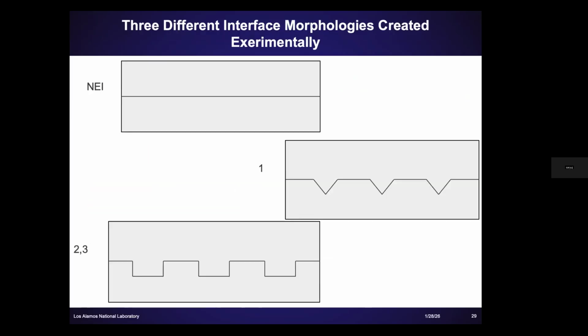How does this compare with experiment or reality? Because molecular dynamic simulations can have their own issues. So to check that, we actually did some experiments. We made three interfaces. One, we basically took two pieces of materials and joined them together using diffusion bonding. Then in one case, we made defects in the titanium. Imagine taking a sharp tool and making a scratch and then doing diffusion bonding. So the interface kind of looked like this versus a square kind of interface. Again, we made the defects in titanium and bonded them together.